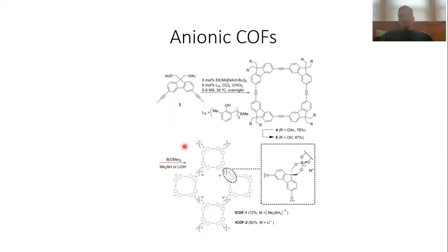Okay, and then you interconnect these squares here with BO4 linkages. So the boron can now make 4 bonds to two different squares, here and here, and these two squares then stand perpendicular to each other, just because of the tetrahedral coordination of the boron.